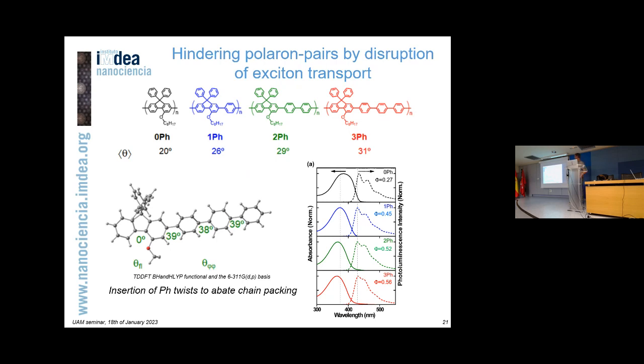So another approach we tried was to introduce twisting units. What happens is that these fluorene units are typically a little steric, and in solution they don't like to twist very much. So when you process them into a film, you get planarity—chains tend to form planar regions, planar domains, where chain packing is very efficient and you get strong interchain interaction. By introducing new units in one, two, or three numbers, we can increase the dihedral angle, reduce molecular packing, and the original idea was that this might help reduce the formation of excimers.